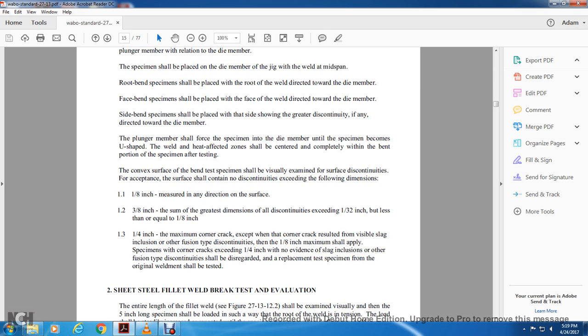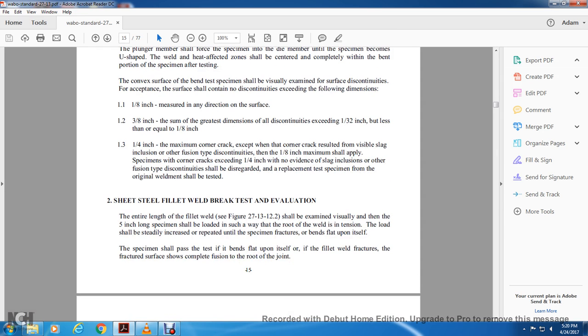1/8 of an inch measured in any direction on the surface; 3/8 of an inch, the sum of the greatest dimensions of all discontinuities exceeding 1/32 inch but less than or equal to 1/8 of an inch; 1/4 of an inch maximum for a corner crack, except that a corner crack resulting from visible slag inclusion or other fusion-type discontinuity shall not exceed 1/8 of an inch maximum. Specimens with corner cracks exceeding 1/4 of an inch with no evidence of slag inclusion or other fusion-type discontinuity shall be discarded, and a replacement test specimen from the original weldment shall be tested.